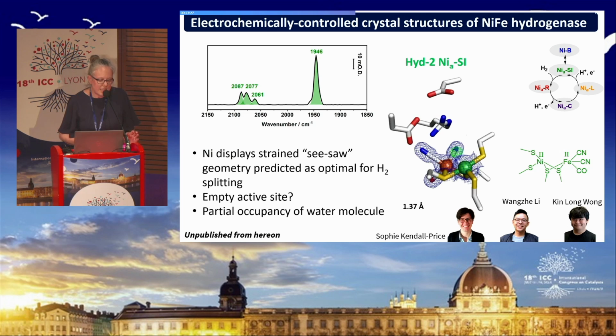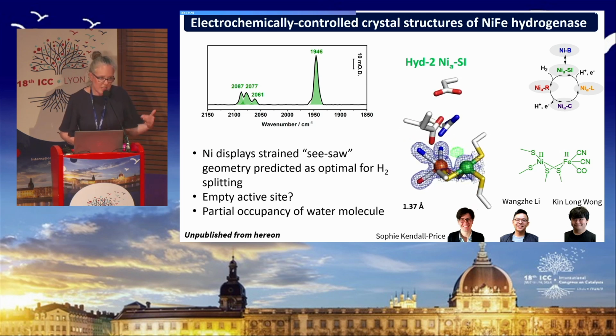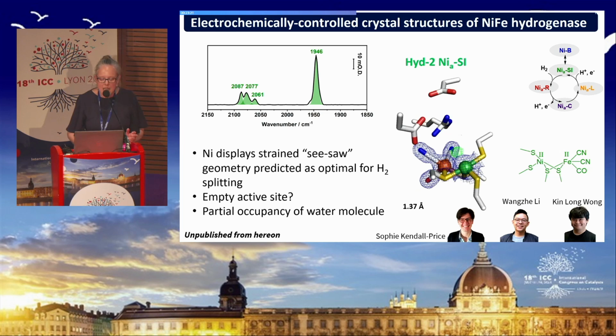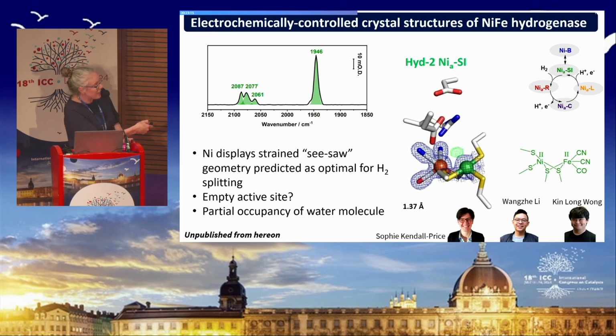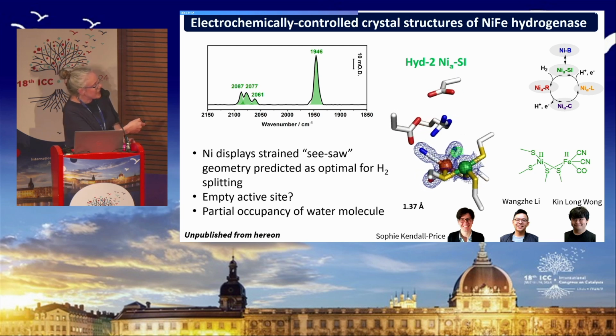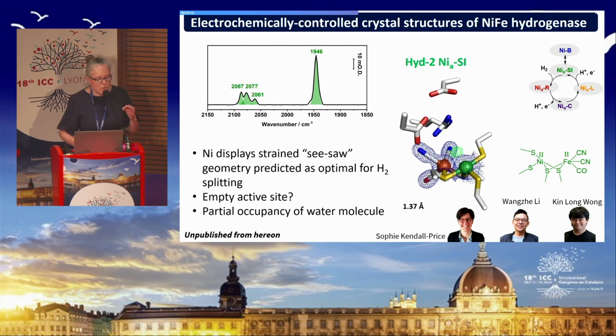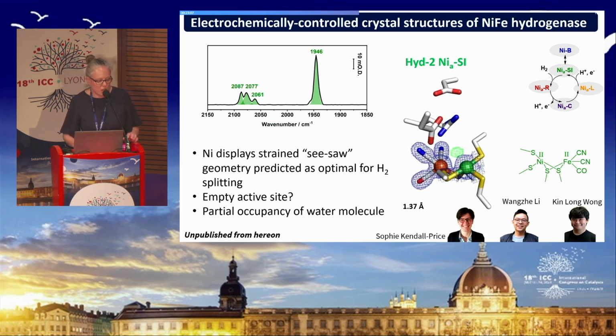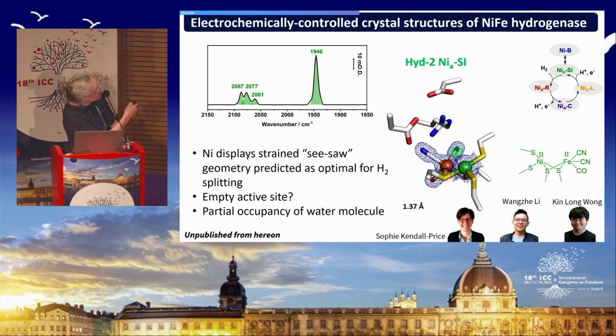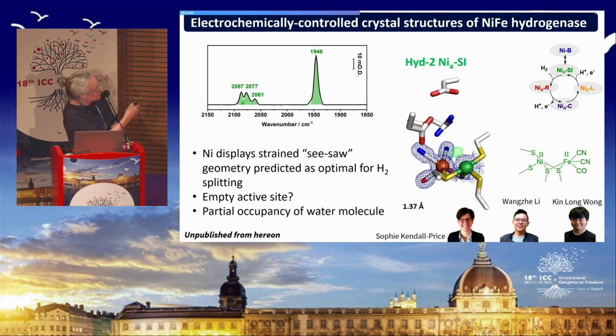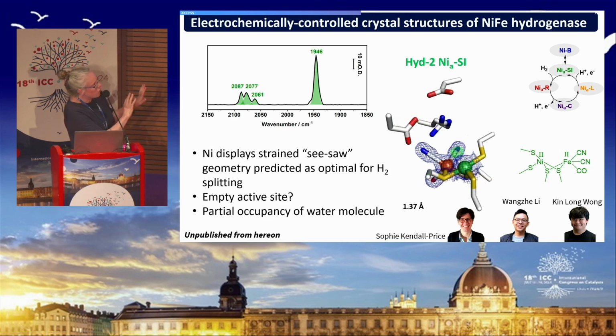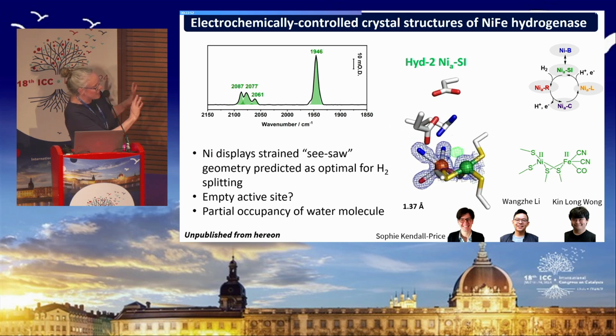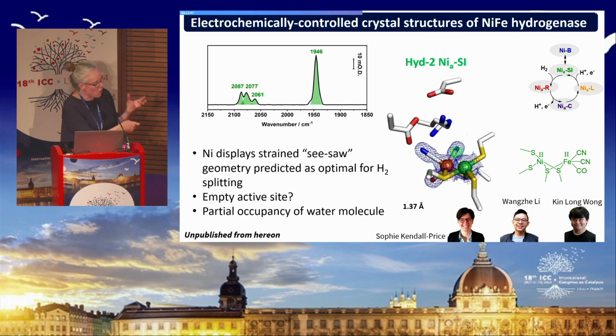The nickel displays the seesaw geometry, which has been predicted from computational work to be optimal for hydrogen splitting. The active site is generally thought to be empty in nickel Si, so it's normally represented like this ChemDraw image over here, but actually we do see electron density between the metals here, which would be consistent with partial occupancy of a water molecule, and that would tie in with what we're seeing in the spectra here, where there's an extra band in the cyanide region. We should only have 2 cyanide bands, and probably what we're seeing is the overlap of a water-bound and an empty active site, where they're similar enough in electron density that the CO bands are overlapping.